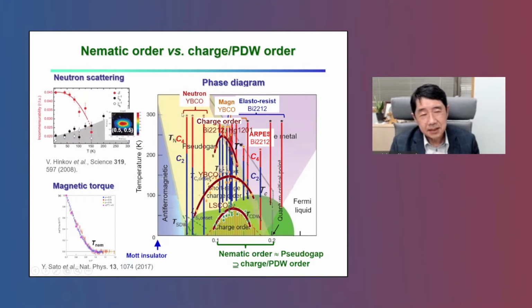But nematicity measured by inelastic neutron scattering, this elongation of one peak, occurs at quite different temperature. And also in this high temperature, low doping region, the origin of the pseudogap is not clear at all, because symmetry breaking occurs in this region, but stops in this high temperature, low doping region.